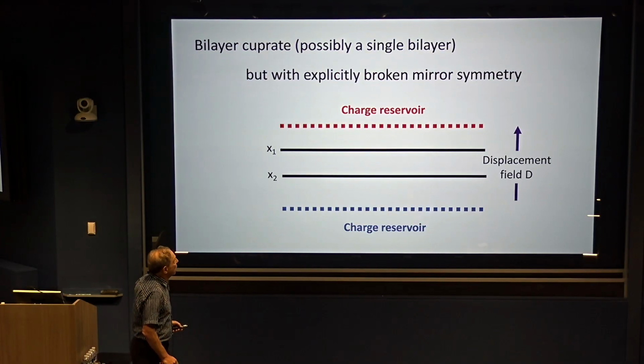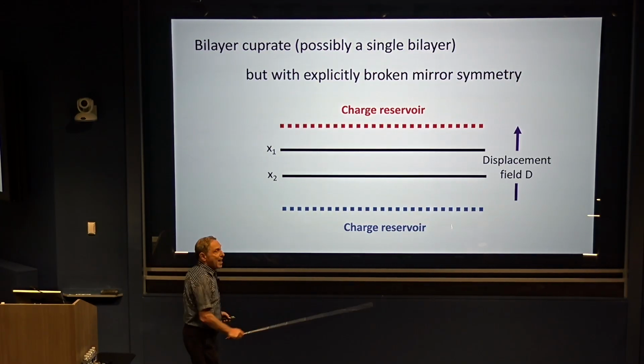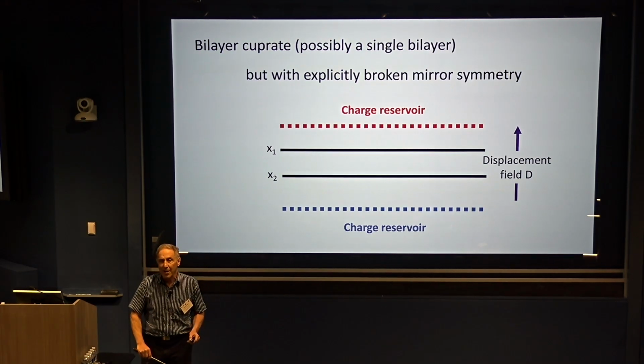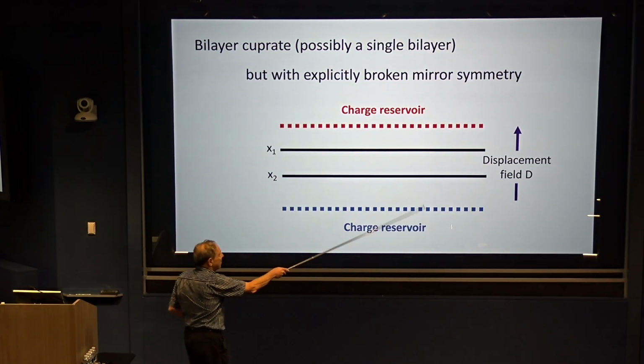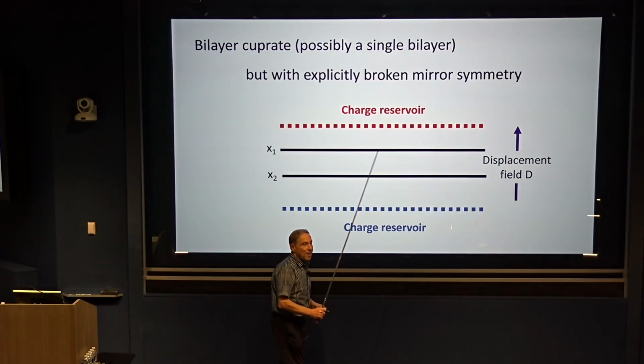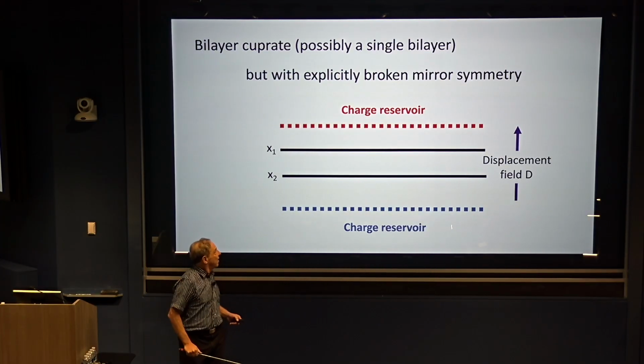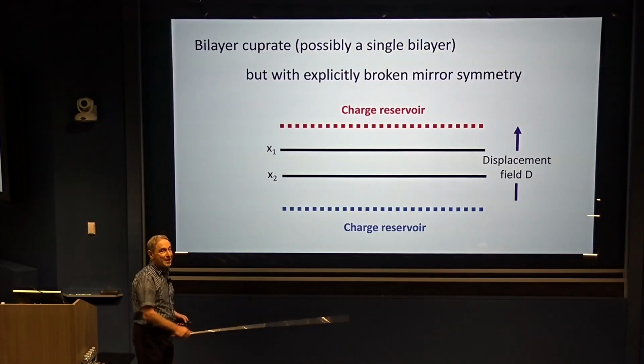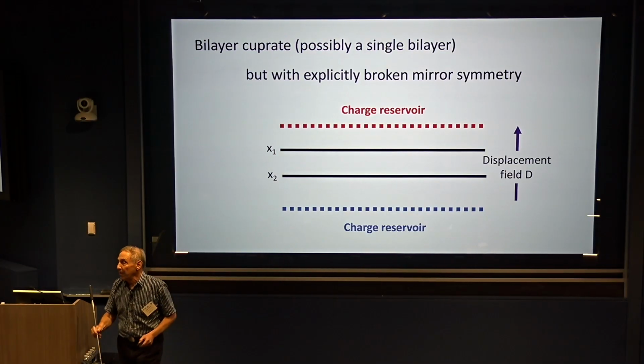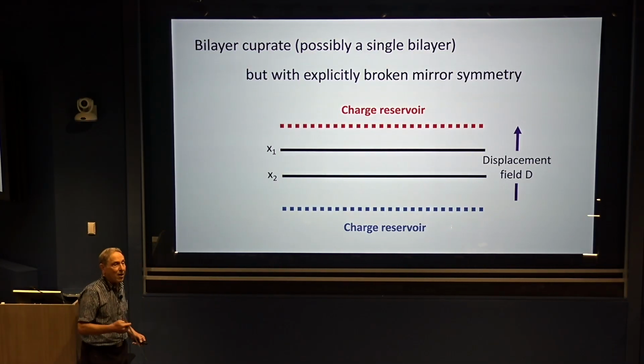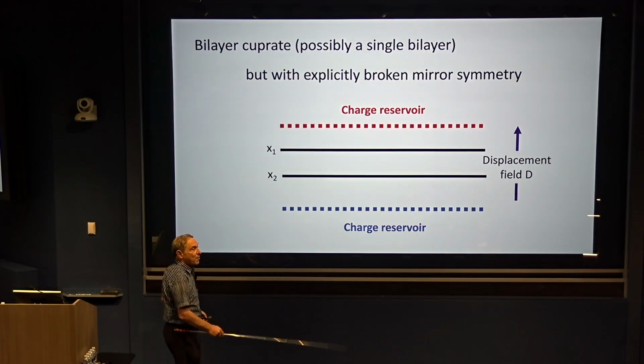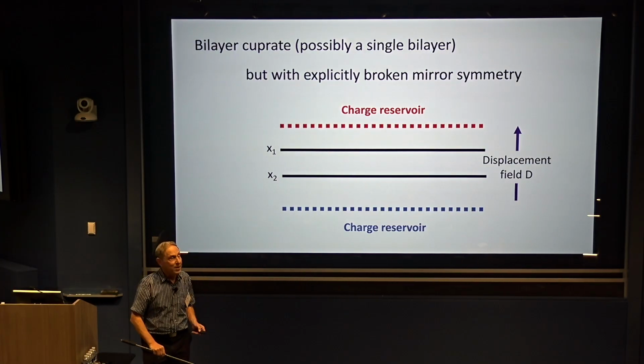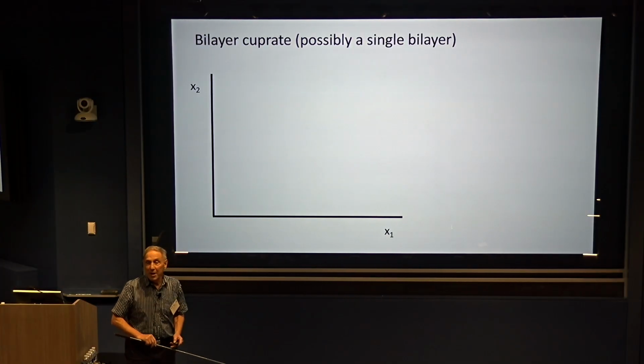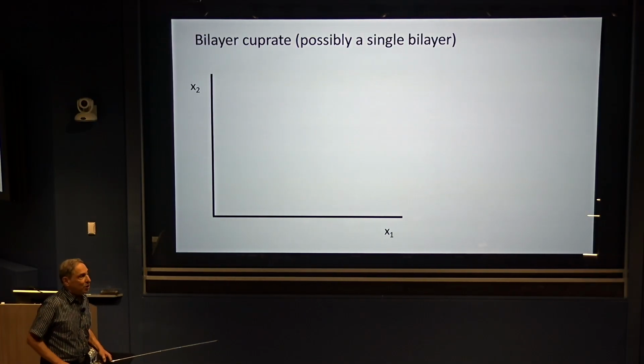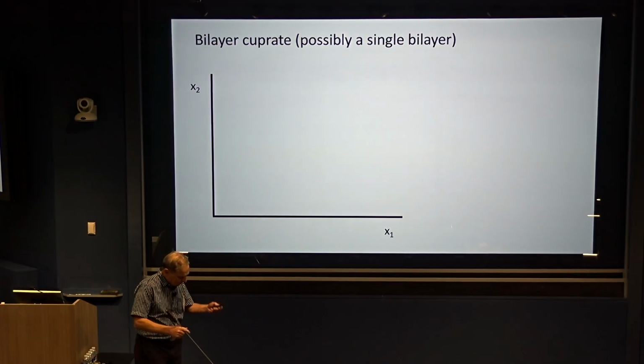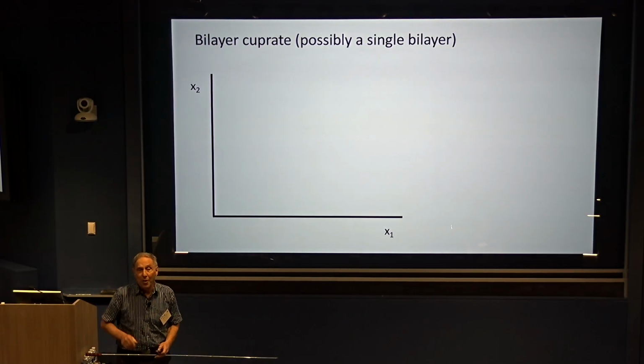But if we were to break that symmetry, either by having asymmetric charge reservoir layers above and below, or, learning from our 2D colleagues, by putting on a big displacement field, then we could imagine a situation where we would separately be able to tune the doping on the upper and lower layer and arrange ourselves so that one of them was overdoped and one of them was underdoped. And then we would explore a new branch, a new avenue, a new dimension of the cuprate phase diagram.